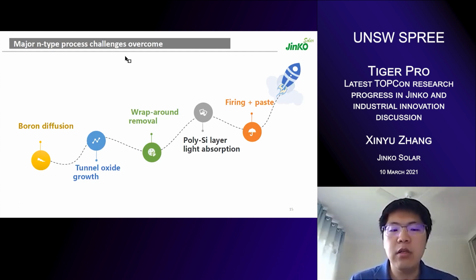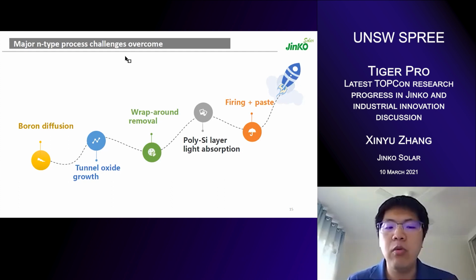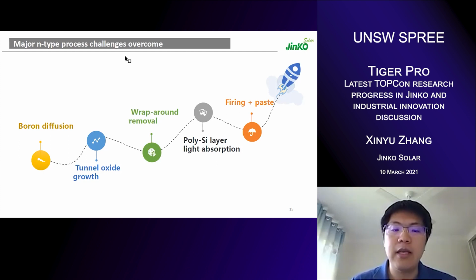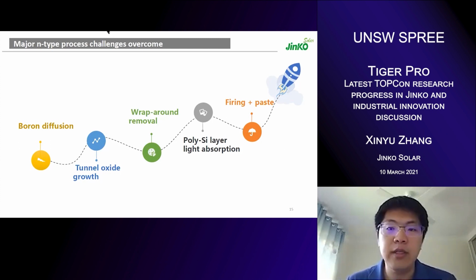The tunnel oxide growth used to be a very important but also challenging thing, but now we have managed to achieve very stable oxide growth with special tools. Although the thickness of the oxide is below 2 nanometers, it can still remain repeatable and reliable. That's pretty much the bottom line of the production. For the wraparound removal, Jinko is using our own sequence and technology, so we never feel there's an issue with this. I know some people in the industry say it's quite challenging, but for us we find it's okay, and the yield rate is well proof of this.